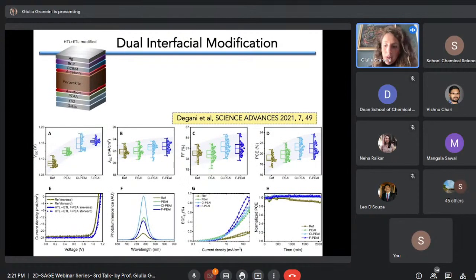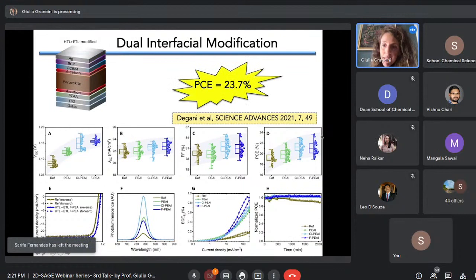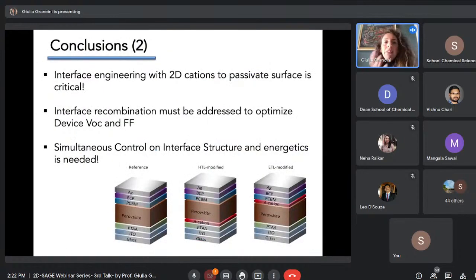Now we combine both bottom and top, and you can see that we could reach very high PCE, up to 23.7%, which is the actual world record for PIN solar cells, due to the concomitant improvement of both fill factor and VOC. Again, you see the PL increases, and also, very importantly, the stability is very, very good with this kind of architecture. So, interface engineering with 2D cations is critical.